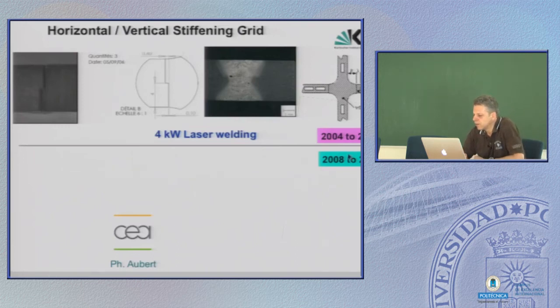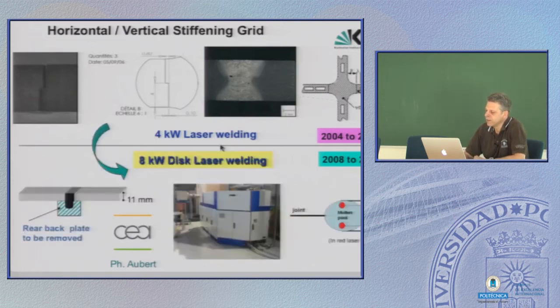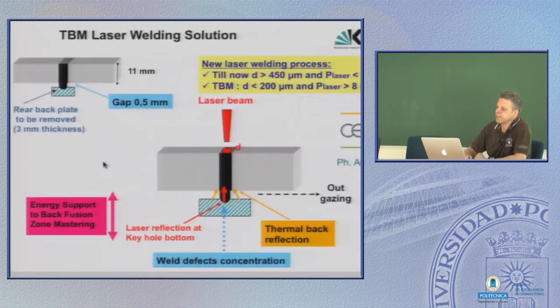Up to 7 years ago or so, 4 kilowatt laser welding was done for that part. Then they updated their equipment, and also here we don't have to go into detail. And the principle of laser welding is that, like in electron beam welding, you don't normally use a filler wire, you just press those parts together and melt them along the weld line.